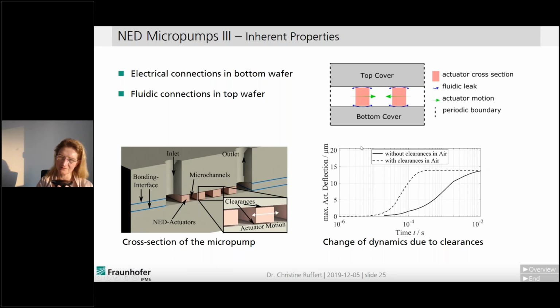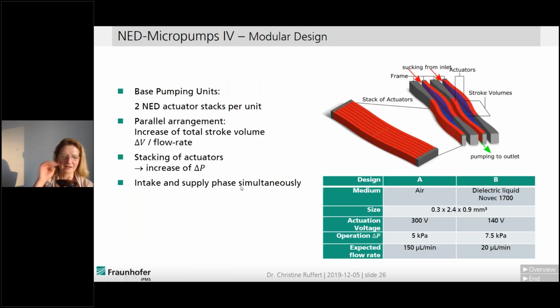So this is a simulation result. You see the maximal deflection depending on the time. And you see that with clearances you have a much higher dynamic in the system. But of course, the pumping rate is smaller because liquid or air is passing through the neighbor chambers. So stacking is very useful to increase the stroke volume, to increase the pressure difference the pump can supply.